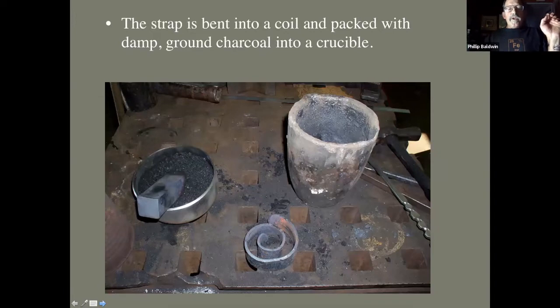So I use the coil because that way we can get it into a crucible and get the maximum amount of surface area exposed to the charcoal dust. You want to use hardwood charcoal. Do not use mesquite charcoal because it has a very high salt content and that interferes with carburization. Next slide, please.